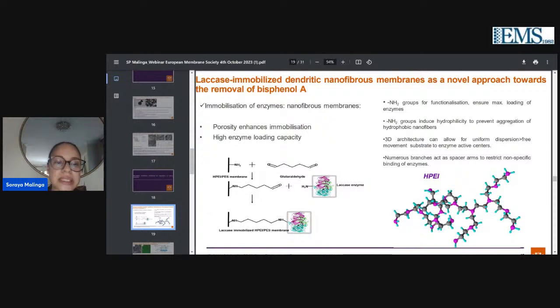So what we did here, we chose to, as I showed in the last few slides, spin the fibers on a commercial membrane. So that was the first thing we did. Then we used a linker, glutaraldehyde, to attach the laccase. So you can imagine the laccase dangling, grafted on the fibers, which are also attached on the membrane as a support.